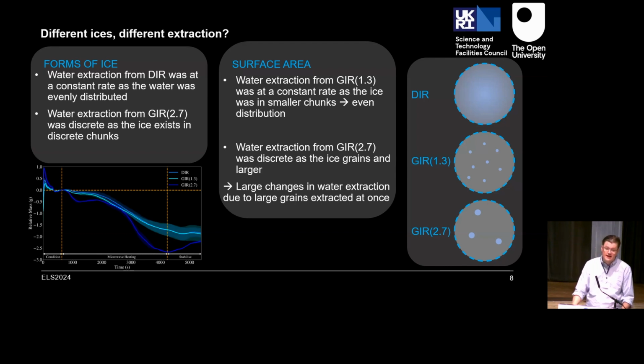So the reason I think this is happening is that as the grains are heated, the larger grains are producing more vapor within a grain, and that leads to a higher pressure, and that leads to a higher water mobility through the sample, so that you're able to produce more water. It's also why it comes out in large chunks. You first get rid of the surface ice, and then these larger ones come through, making use of the void spaces already left behind from the previous ice grains. So it seems to suggest that the larger ice grains might be more susceptible to microwave heating, but obviously this needs to be looked into further to analyze what's really going on.